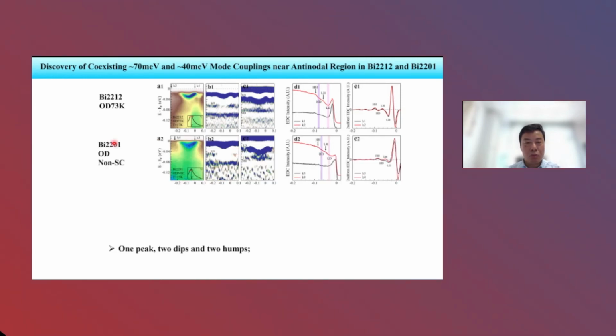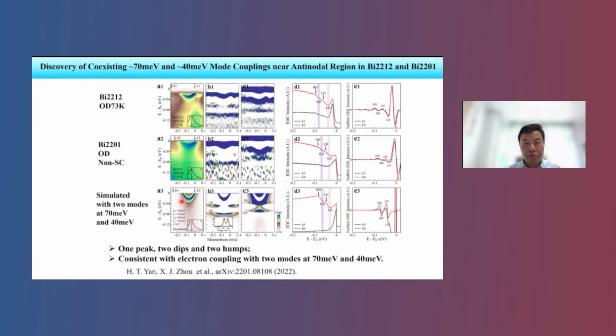You can use Bi2201, heavily overdoped, non-superconducting. You can also see two flat bands here. And you can also do a simulation. If we have two mode couplings here, even though the phonon energy is larger than the band bottom energy, you can still see two flat bands. That means in both Bi2212 and Bi2201, near the antinodal region, we can also see the two coexisting 70 millivolt and 40 millivolt mode couplings here. So this is totally new. Previously, it was never observed before, but now we can really see that these two mode couplings are coexisting.